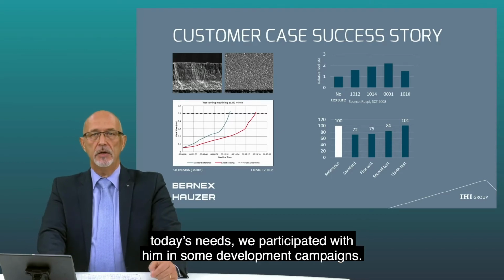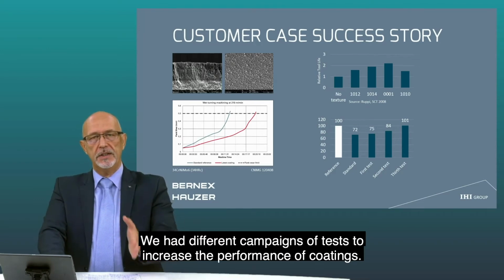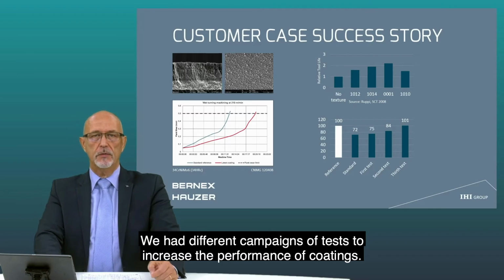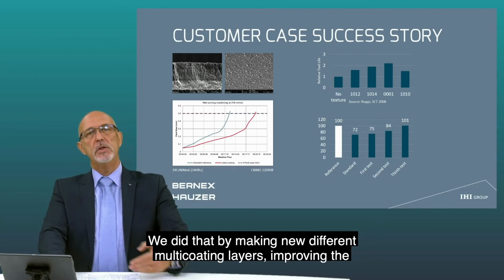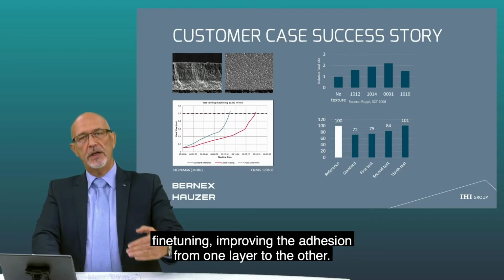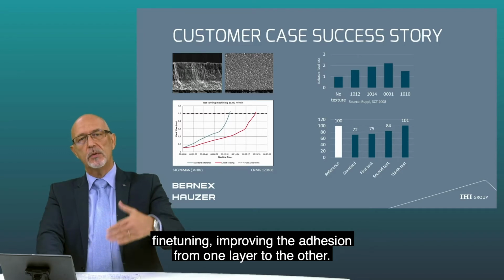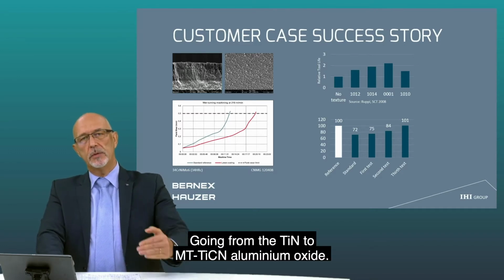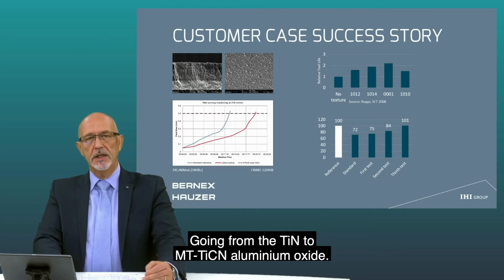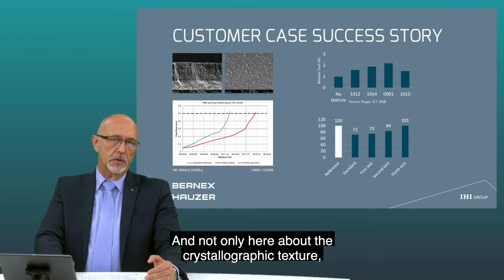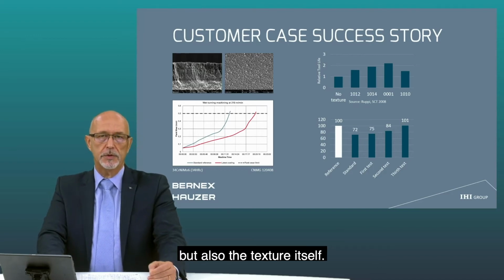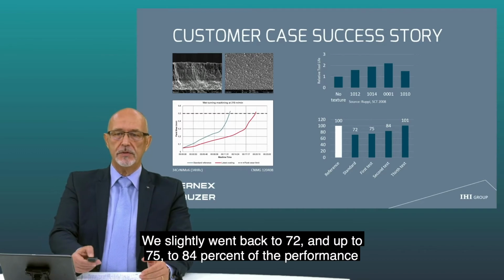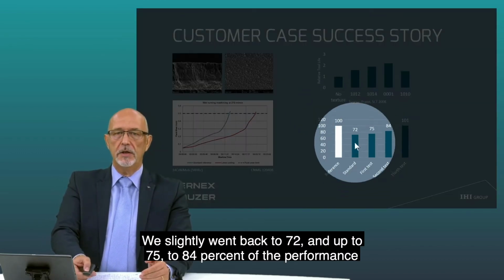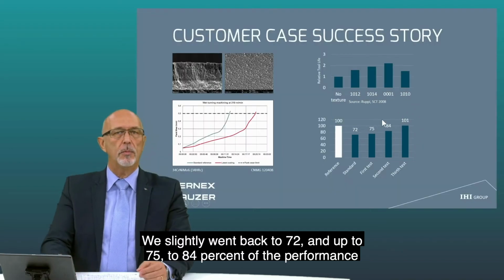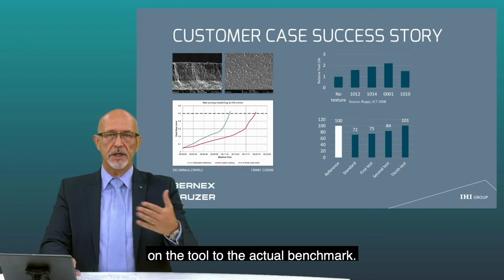To allow him to bring the machine back to being a tool that he can use for the actual needs, we participated with him in development campaigns, with different campaigns of tests and increasing the performance of the coating. We did it by making new multi-coating layers, fine-tuning, and improving the adhesion from one layer to the others, going from TiN, MTTiCN, aluminum oxide, and working not only on the crystallographic texture but also the texture itself. And so we slowly brought back from 72 to 75 to 84% of the performance of the tool relative to the actual benchmarks.